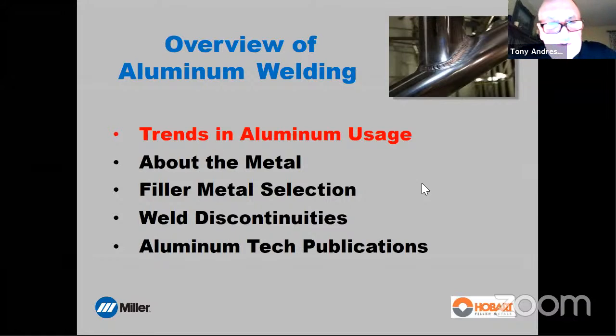Okay, then weld discontinuities. There are a couple of discontinuities that are pretty specific to aluminum, and one of them you'll all know, I'm sure, if you've worked with aluminum, is porosity. It's always an issue. It raises its head continuously. So I'm going to look a little bit at porosity, what it is, where it comes from, and how we might prevent it. And the other one is hot cracking, solidification cracking. A lot of the aluminum alloys are very solidification crack sensitive. And I want to explain why that is and how a welding engineer can design his welding procedures and filler alloy selection to combat hot cracking issues. And then the last section is going to be technical publications. As I said earlier, I'm going to go through a list of maybe 6, 8, 9, 10 publications that I consider to be very useful if you want to learn more about this particular subject.